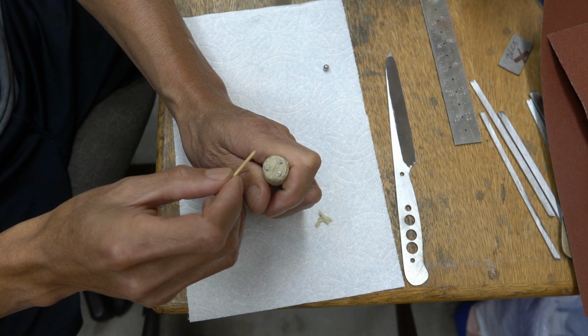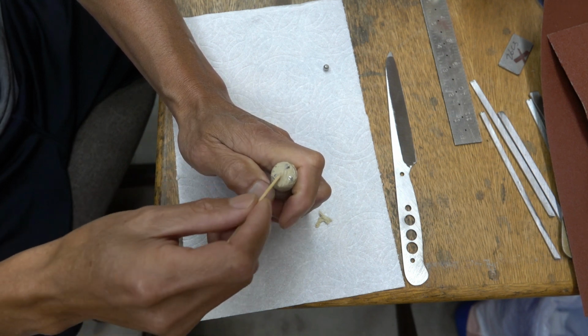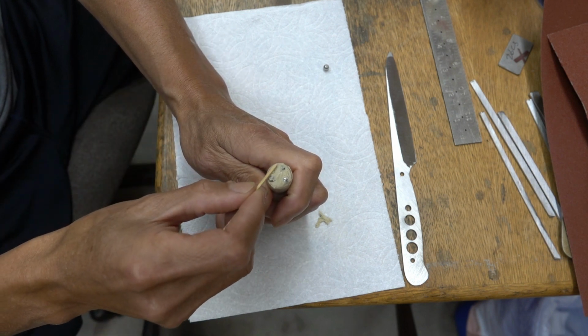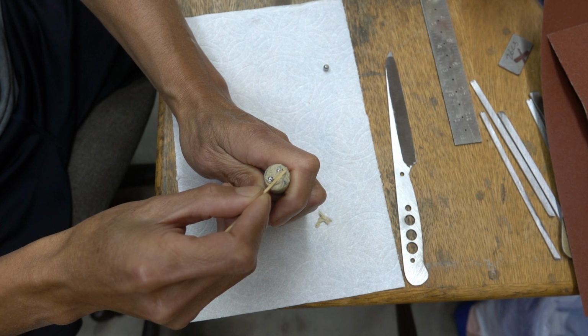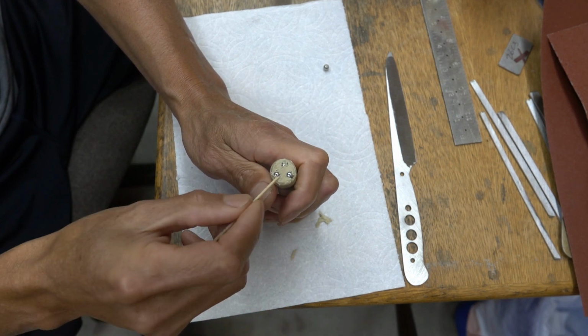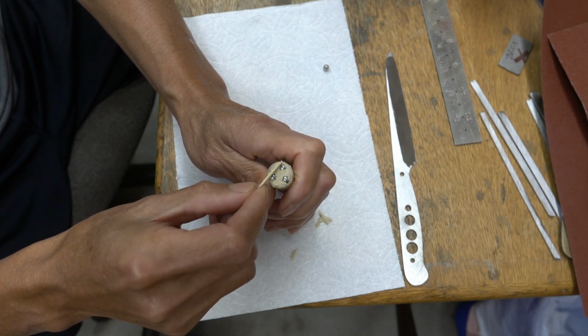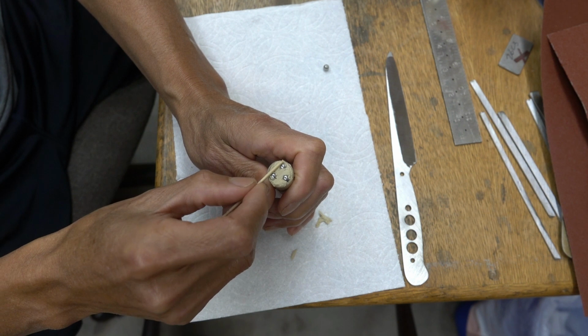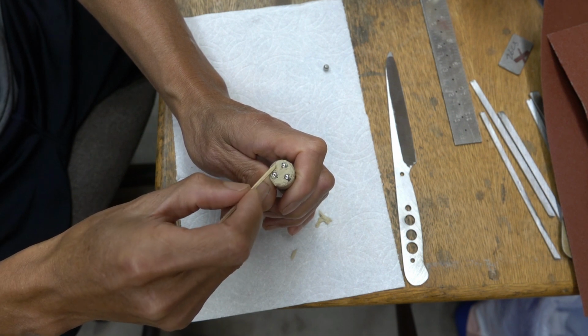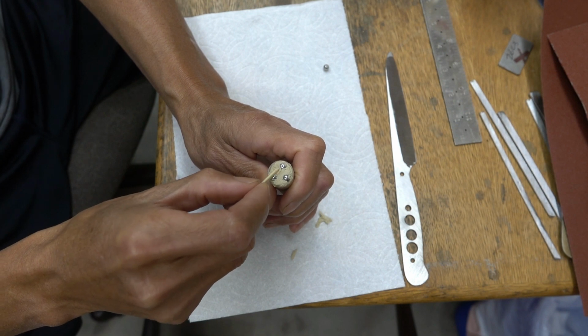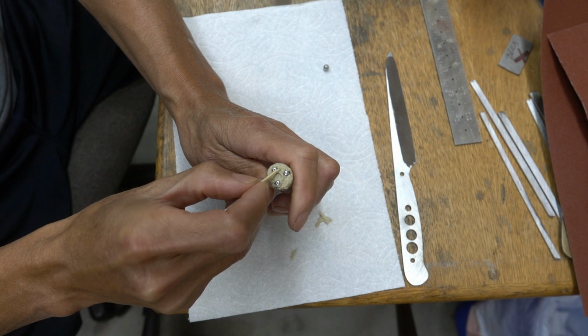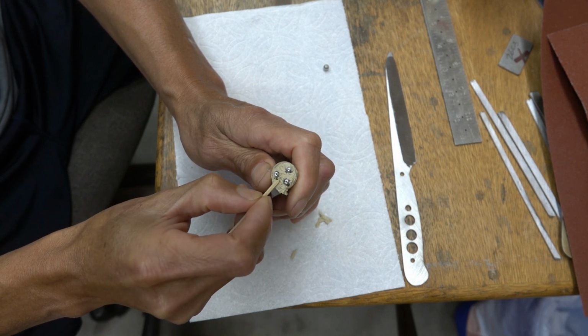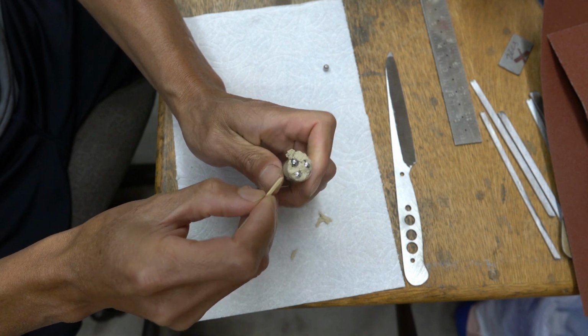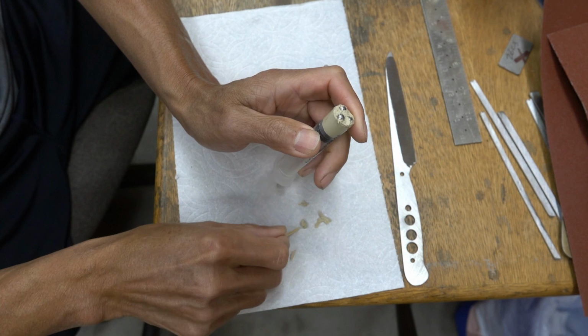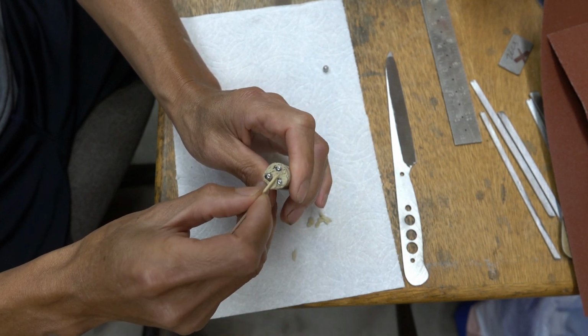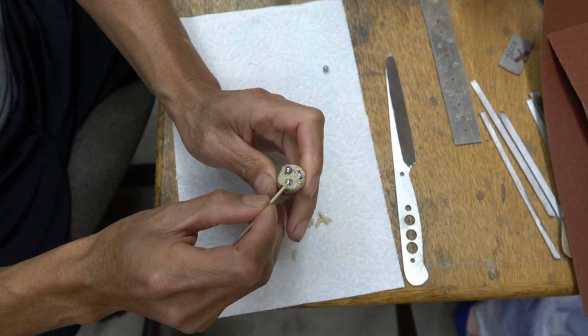So now, let me push this up a little bit, right? So now the same thing like before. If I try to rub it, most of the carbide is still beneath the surface, right? So now the fixed abrasive goes right over the top of the carbide, while the loose abrasive goes between and undercuts the carbide, like so. Remember, I rotated because I'm doing clockwise and counterclockwise to remove material, in this case the matrix.